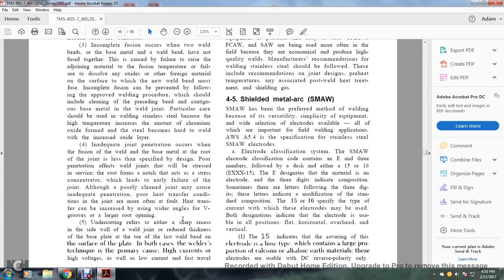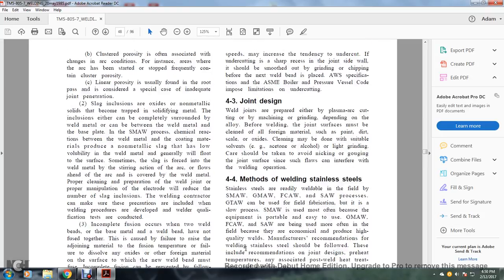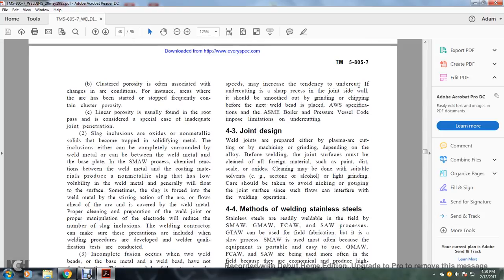Undercutting refers to either a sharp recess in the side wall of the welded joint, reducing the thickness of the base plate, or at the toe of the last weld bead on the surface of the plate. In both cases, the welding technique is the primary cause: high currents or high voltage, as well as low currents with fast travel speeds, may increase the tendency to undercut.